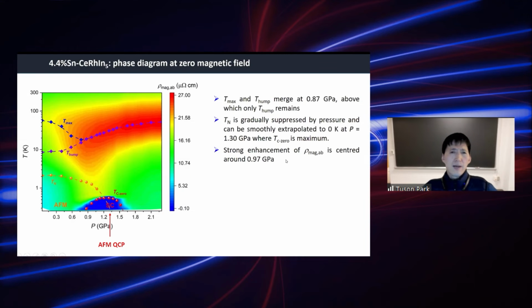So this is 4.4% tin-doped CeRhIn5, the contour plot of magnetic resistivity, where the total resistivity is subtracted by the phonon part. You can see this antiferromagnetic phase boundary nicely extrapolated to around 1.3 or 1.4 GPa.